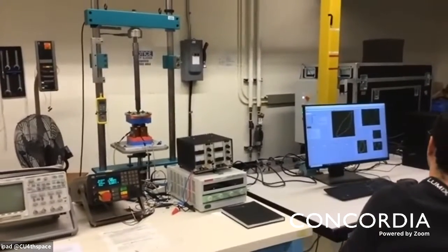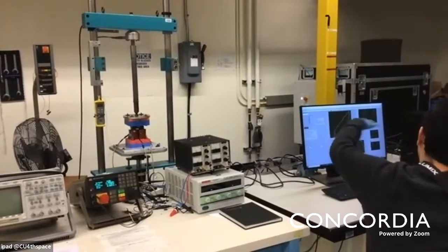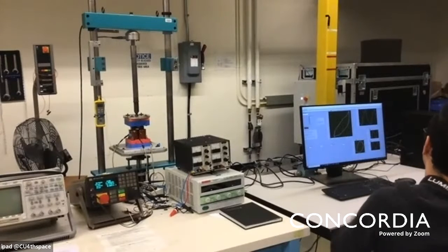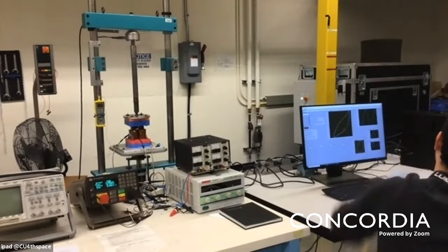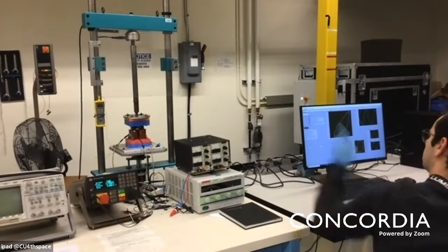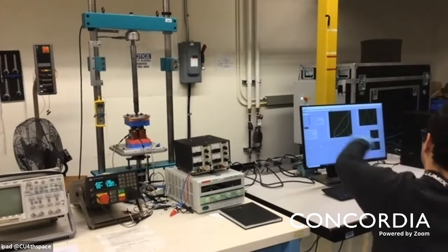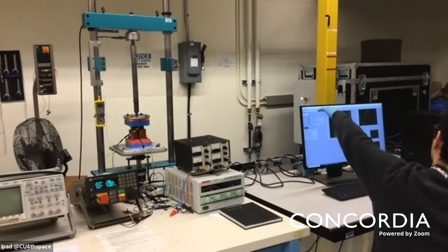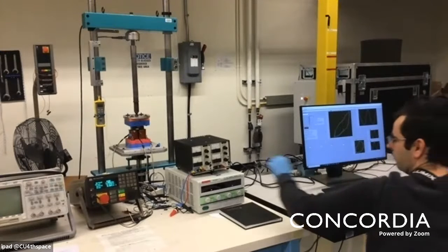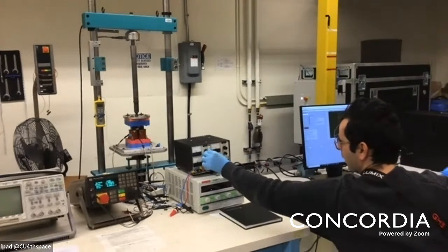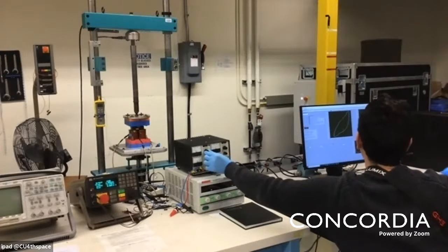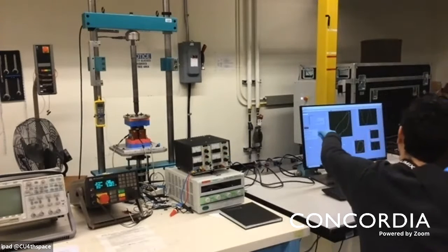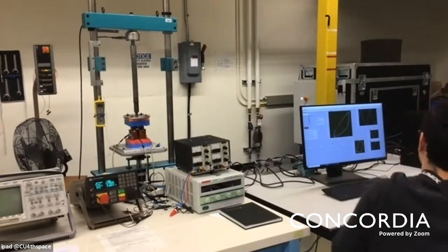The force also decreases, because under compression, tension will give positive force and compression will give negative. So the force changes from around 30 to around -50. If I increase further, even more force will be generated inside the MRE. So this shows this property dependence.